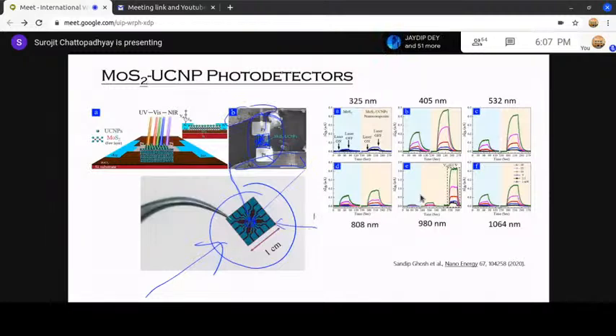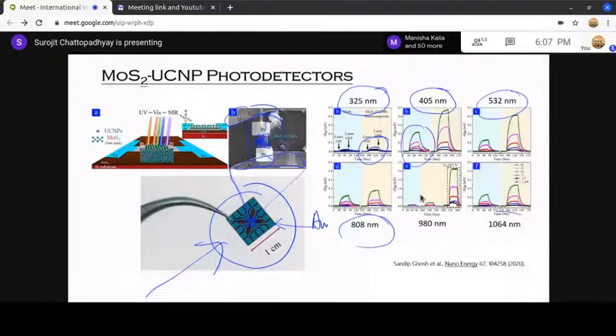So we make these devices, the single flake of MoS2 with the UCNPs, and you shine different colors of light, you get current. So you see, this one I shine UV light, then I get this current, okay? I shine blue light, I get this current. Green light, then IR light, far IR light, then you get current. So basically you are making photodetectors out of these materials, okay? And they have very high responsivity. This is only happening because we are working in the nanoscale.